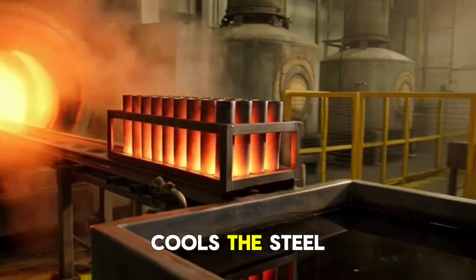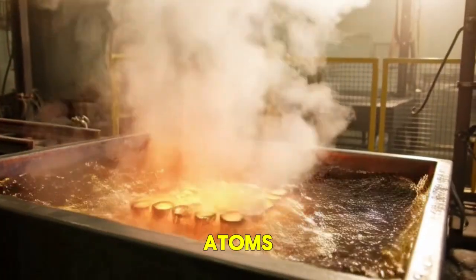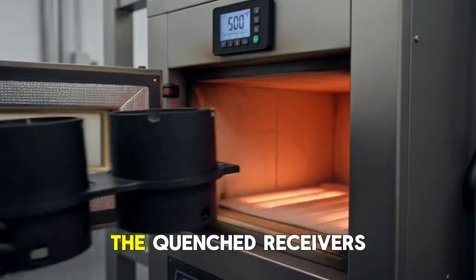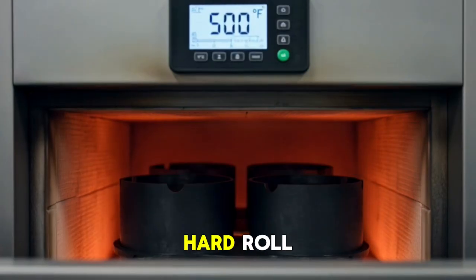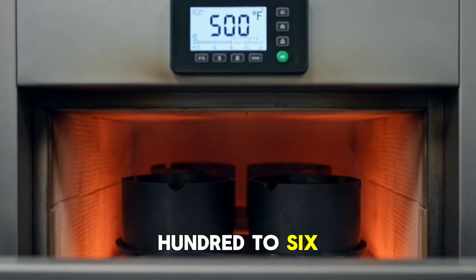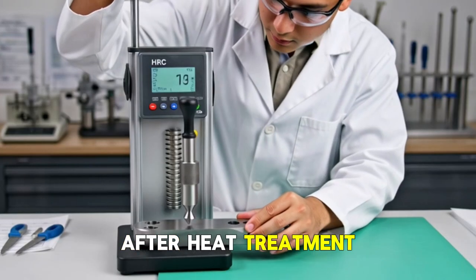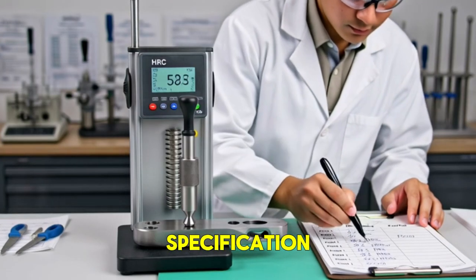The oil quench cools the steel fast enough to trap the carbon atoms, creating a hard martensite structure. The quenched receivers are now extremely hard and brittle, so they undergo tempering, around 400 to 600 degrees Fahrenheit. After heat treatment, hardness testing verifies the steel meets specification.